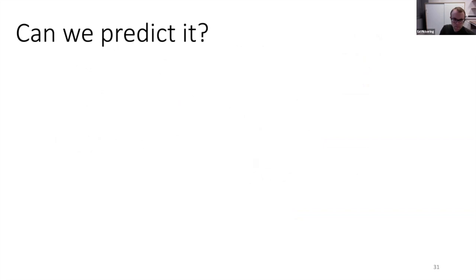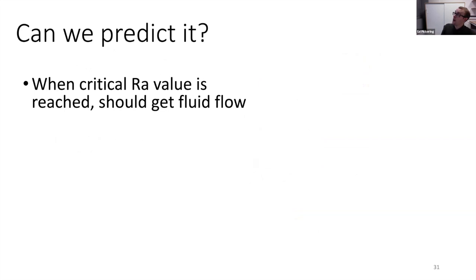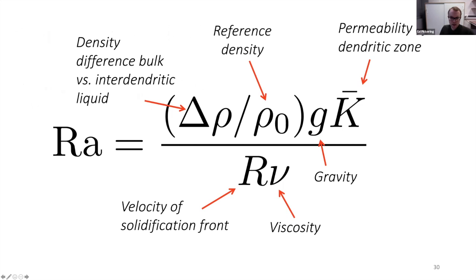So the idea with using this Rayleigh number, and the use of the Rayleigh number in this context was pioneered by Christoph Beckermann in the US, is that when the Rayleigh number reaches a critical value, we should get fluid flow. So what you do is you create a simple thermal model of your ingot. You input values, you can get some of these from things like JMatPro, and you can estimate some things based on dendrite arm spacings and that sort of thing.